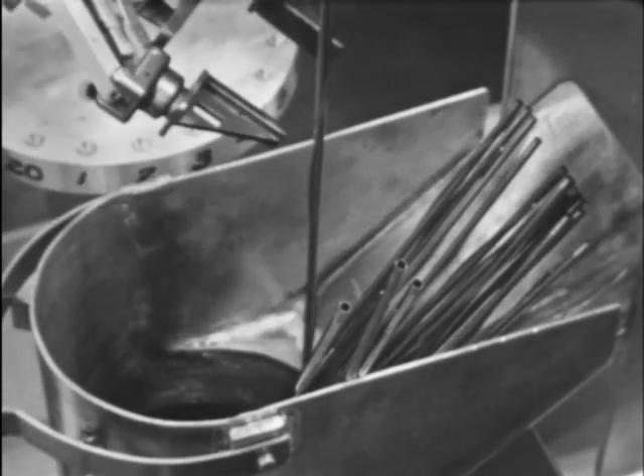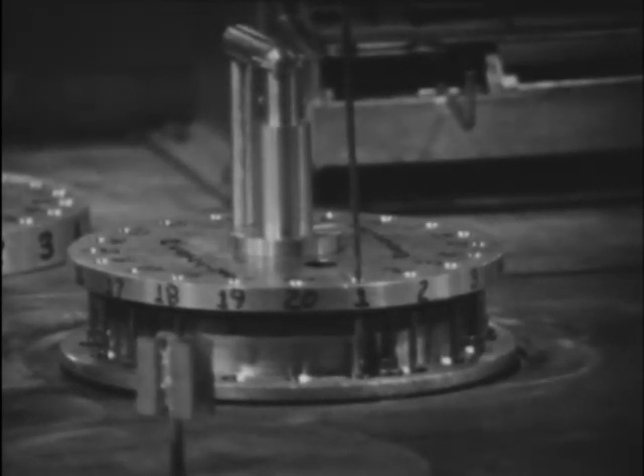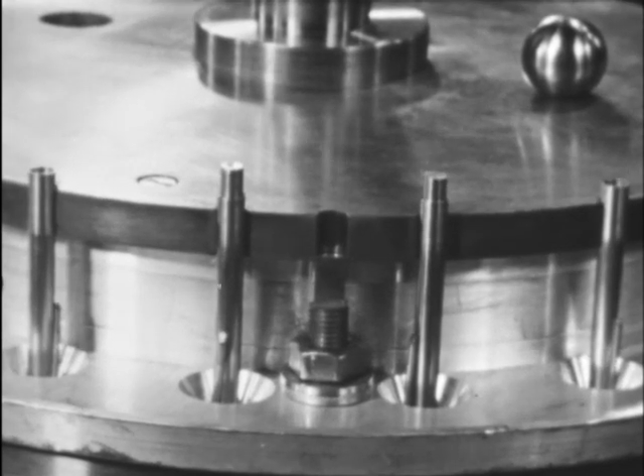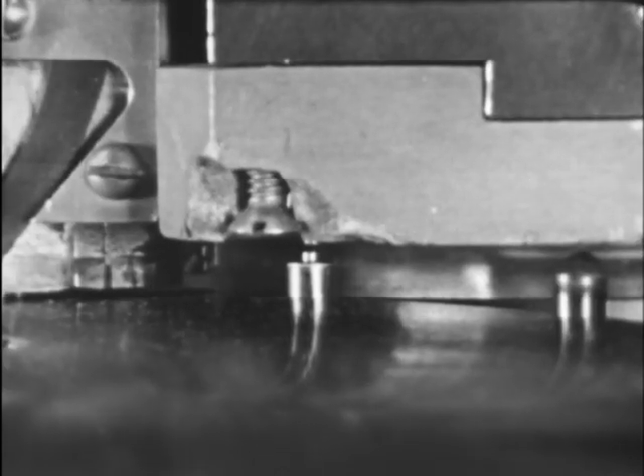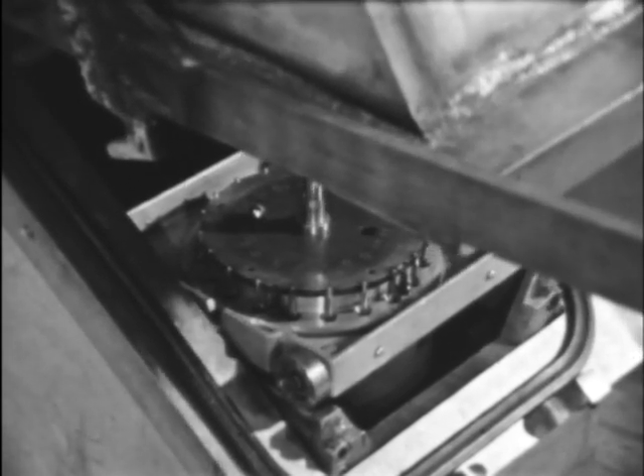Jacket tubes with a predetermined quantity of sodium are loaded in a magazine. The fuel pins are inserted and the sodium is melted under gentle vibration to permit settling of the fuel pin, then transferred to the welding station. Restraining plugs are inserted and welded to the jacket by capacitor discharge. The fuel is once again jacketed and can be returned to the air cell.